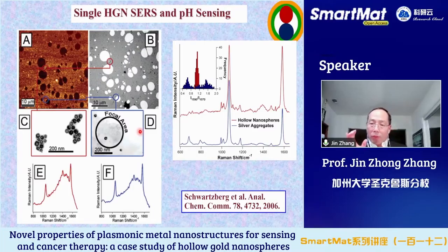Okay, one application we did was SERS, and this is a single, not any source, it's a single nanoparticle source. We compare a single HGN, hollow gold nanosphere, with single silver nanoparticles or aggregate nanoparticles of silver, and we demonstrated that the hollow gold nanosphere is a much better SERS substrate in terms of consistency, not sensitivity, but consistency, as illustrated here.